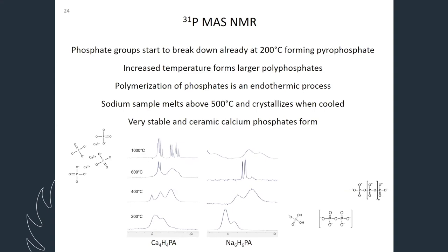If we instead look at the phosphorus atoms in those phytate groups, then we can see at 200 degrees, the peak close to zero there. That's one of the peaks comes from the original phytic acid, and the other peak comes from pyrophosphate.